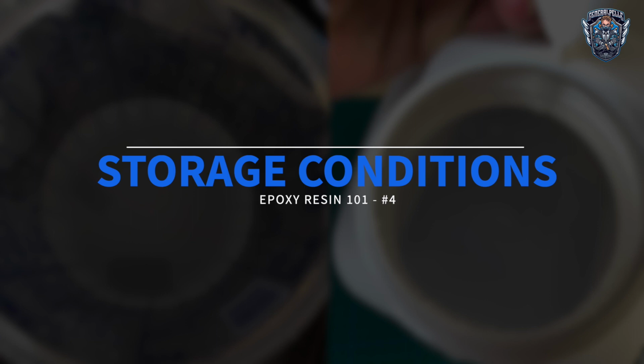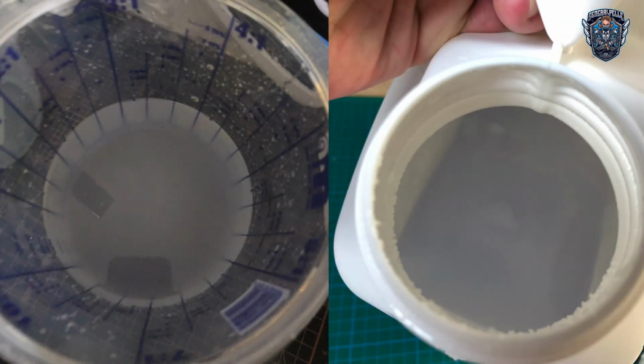So here is the point. I made a huge mistake after I bought that product a couple of months ago. I put it in the basement while it was too cold outside, probably under 15 degrees. And that changed the epoxy resin's state of matter into its hard crystal form. I first thought I could throw it away and order a new package. But like water, the state of matter can be changed by heating the material. So I put the package in a 60 degrees water bath for around 20 minutes and the liquid was clear again and could be used after it had been cooled down for a while.